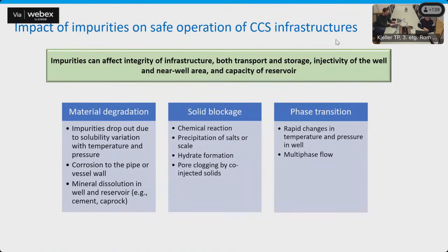Another aspect is unsafe operation of CCS infrastructures. Impurity can affect the integrity of infrastructure, both transport and storage. For example, material degradation: the impurity can drop out because the solubility varies with temperature and pressure, and one impurity can affect another impurity's solubility, so it makes the situation complex. For example, if water drops out to form free water and reacts with some reactive impurities to form acid, then people can risk corrosion of the pipes and vessel walls, and also mineral dissolution in the well and reservoir.